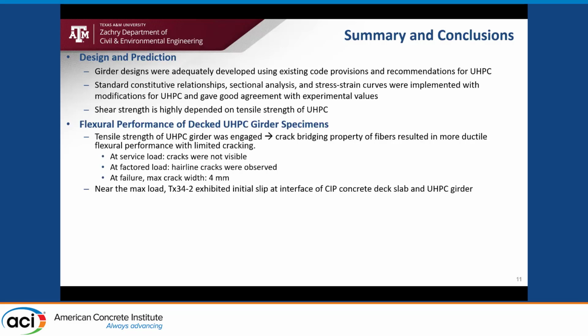The crack bridging properties of the fibers was very effective in getting ductile behavior. The performance of the girders under service conditions was really good, with no cracking and mainly hairline cracks beyond factored load. We noticed one additional thing for the second specimen. Near the failure load, we observed an initial slip at the interface of the cast-in-place deck slab with the UHPC girder.